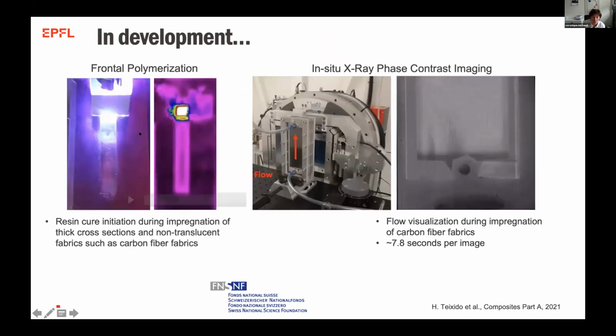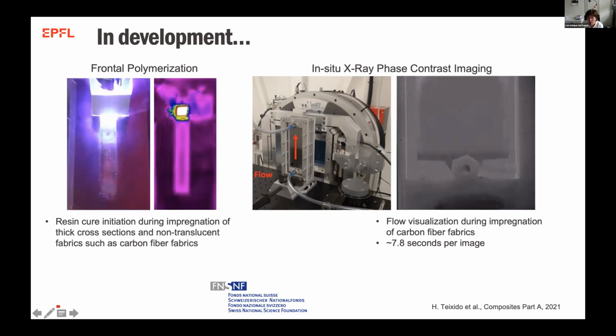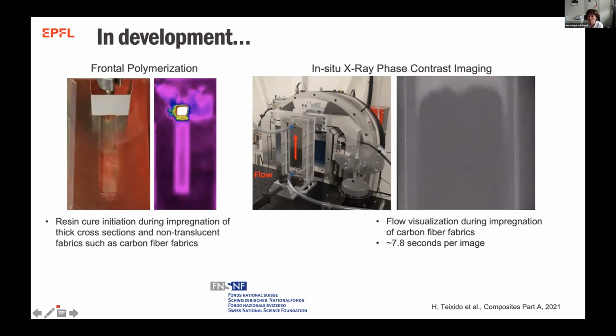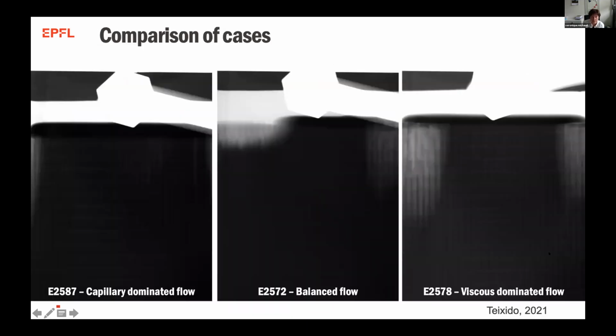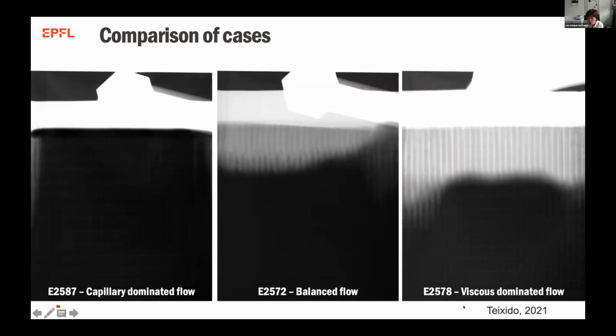Our work in progress is to continue to look at this snapshot. So we can do it by doing thick cross-section, non-translucent fabrics using frontal polymerization, and it's in progress. And here, at the beginning, it was really burning. Now it's not burning so much anymore, we've improved. And then the other way is to do a flow visualization with X-ray phase contrast imaging. So this looks big, but it's an X-ray detector in the back and some gratings. And I will show you a bit more about those guys. Next slide. Yes. So this is a comparison of cases which I just got from Elena.